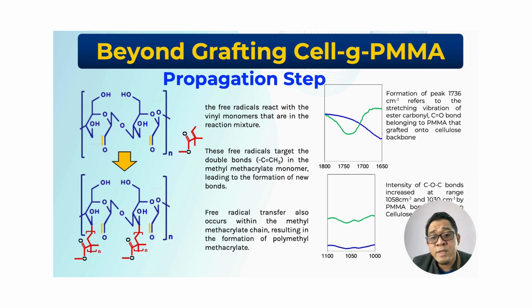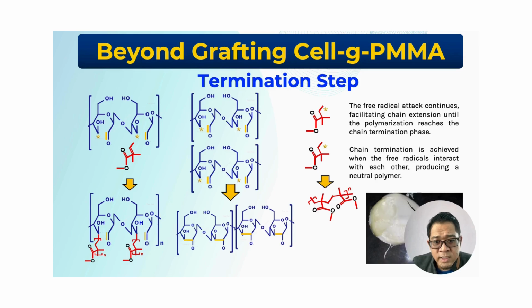And for the proof, the formation of a peak at 1,736 per centimeter refers to the stretching vibration of the ester carbonyl C double bond O belonging to PMMA grafted onto the cellulose backbone. The intensity of the COC bond increased in the range 1,058 per centimeter and 1,030 per centimeter from PMMA grafted on cellulose. And lastly, the termination step occurs, and the free radical attack continues the polymerization of the chain. The chain termination is achieved when free radicals interact with each other, producing a neutral polymer.